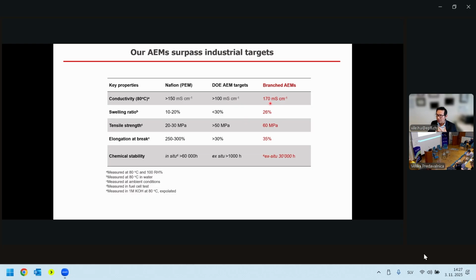So in terms of conductivity, we are very good. In terms of swelling ratio, these are also not bad because it has hydrocarbons, aromatic ones. And in terms of tensile strength, we are also really high. And in elongation at break, we are less elastic than Nafion, but again better than the DOE target. In terms of chemical stability, we have tested and can extrapolate that from the hydroxide stability point of view, it should be more than 30,000 hours because of our rigid and stable functional group.